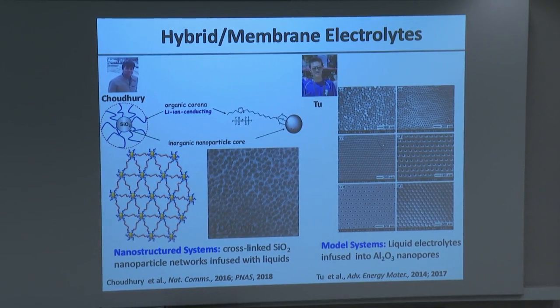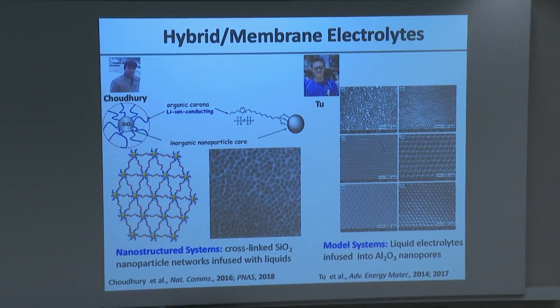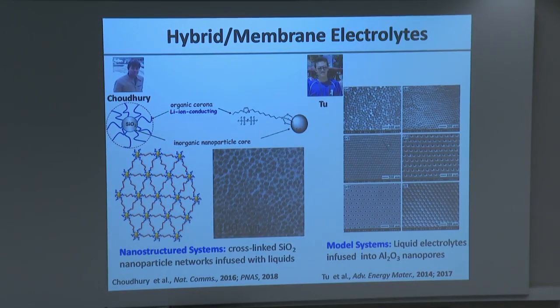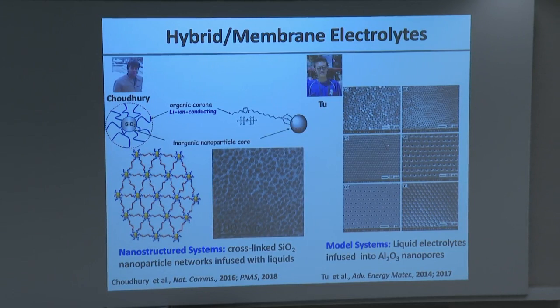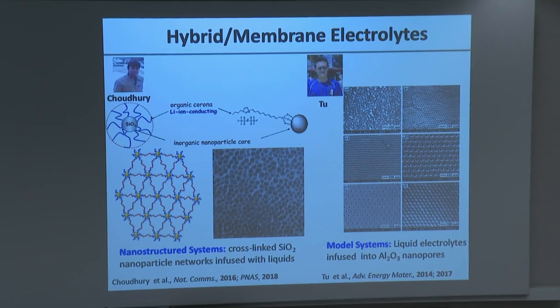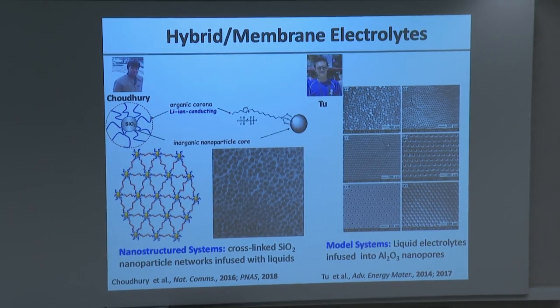The other system is cleaner and actually more amenable to fundamental studies. So what we decided to do is to create using anodized alumina, which makes very beautiful porous structures, where you could control the size of the pores by the voltage at which you create the porous structures, to create things that have pore sizes that range, I will show you in a minute, all the way from a few tens of nanometers to hundreds of nanometers. And these are straight pores, so we can test the predictions somewhat more rigorously.